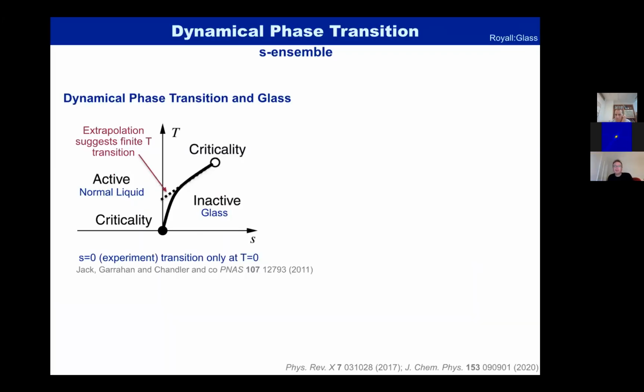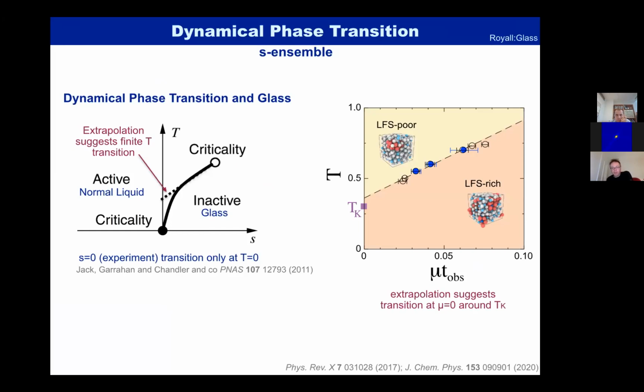So I said that there's this dynamical phase transition of facilitation, and that's the cartoon on the left, our data is on the right. We have the transition between two different phases, and we have this quantity mu, which is a biasing field to push us through the transition. And mu equals 0 is the experimental case. Our simulations are sampled at non-zero mu, but as we drop the mu,